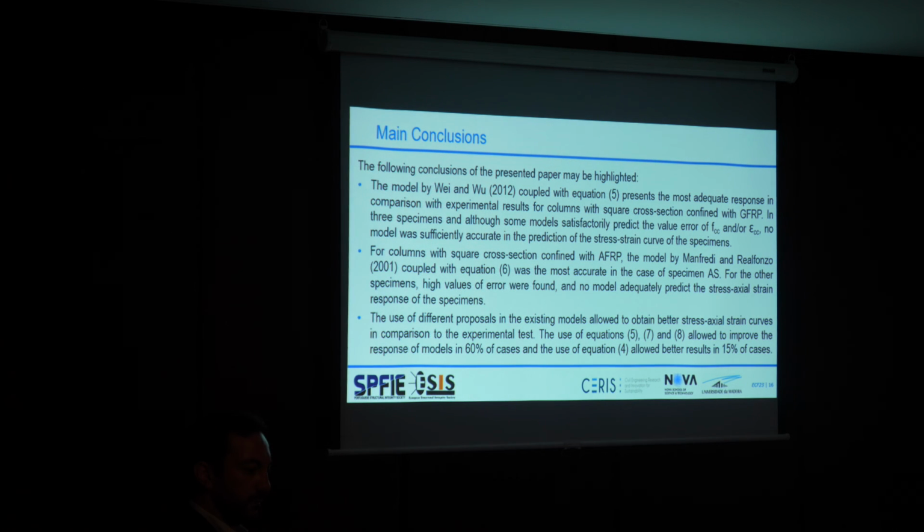The use of different proposals in the existing models allows us to obtain better stress-axial strain responses compared to just testing the model without these equations. And the use of equations 5, 7, and 8 allows improving the response of the models in 60% of the cases, while the use of equation 4 allows better results in 50%.